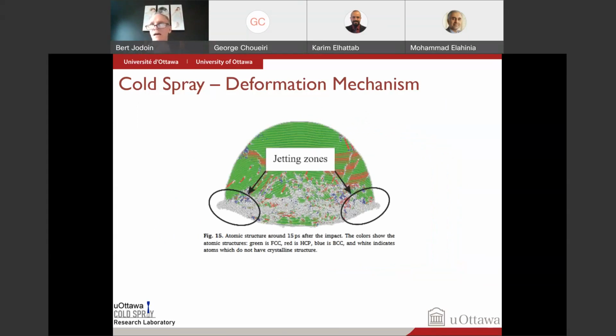molecular dynamics. The problem with molecular dynamics is we cannot model a 10, 20 micron particle. We need to have very, very tiny particles, but still it allows us to figure out what's going on. So you can see here, based on molecular dynamics, so that means we model atom by atom and we follow them as we deform them. You can see that based on the molecular dynamics model, what you have in gray are atoms that are not following the crystal structure initially found in the material. They're now not behaving as a crystalline structure. So that's what happens there.